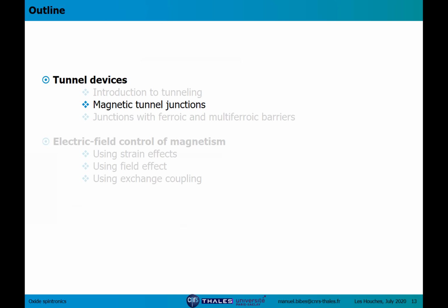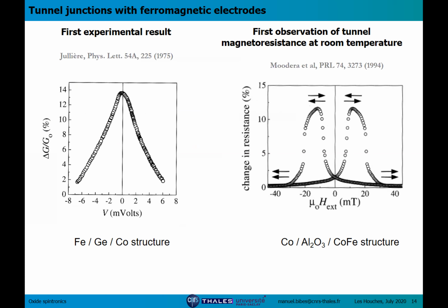So now let's move to magnetic tunnel junctions. We will now forget about the superconducting electrodes, and the junctions I will describe now involve two ferromagnetic electrodes separated by an insulator. The very first experimental result on magnetic tunnel junctions is shown here. It's from a paper from 1975 by Michel Jullière, who was a professor in Rennes in Brittany, in France. And he was working with this kind of structure: iron, germanium, cobalt.